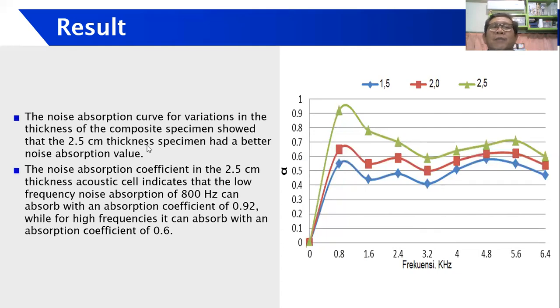The noise absorption curve for variation in the thickness of the composite specimen shows that the 2.5 centimeter thickness specimen had a better noise absorption value. The noise absorption coefficient at the 2.5 centimeter thickness shows that low frequency noise at 800 Hz can be absorbed with an absorption coefficient of 0.92, while high frequency noise is absorbed with an absorption coefficient of 0.6.